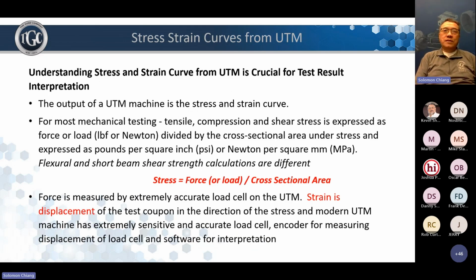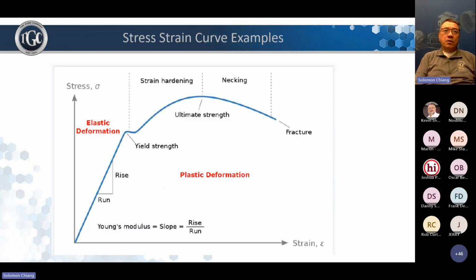One thing about the universal machine is that nowadays they're all digitized and very sensitive. Their load cell can be as accurate as down to 1 pound. The universal machine tests both the load and the displacement of the coupon, and can measure down to a fraction of a thou or less. That is important because we need to know the stress-strain behavior of the material under test, beyond just having a number for how much force it can withstand. And this is a typical stress-strain curve obtained from a universal testing machine.